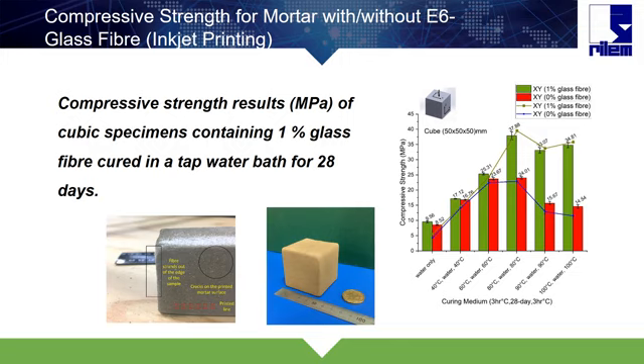After checking these materials with the glass fiber, we get very good results for the cubic shape of the sample with an 80 degree treatment in post-processing, and we get about 37.88 megapascals when we have 1% glass fiber in the printed sample. However, we couldn't put too much glass fiber in the specimen because of blockages that happen in the back of the printer chamber. So that's why we are trying to use a minimum of 1% to get a good result for such printed specimens.